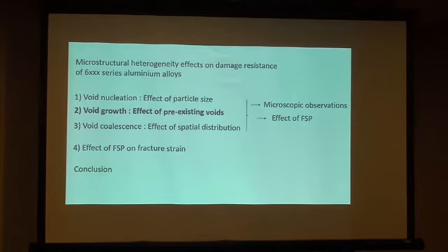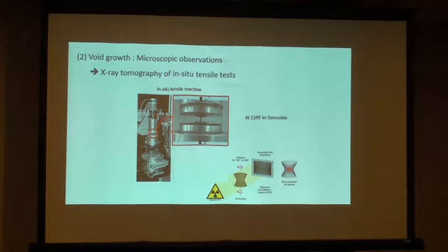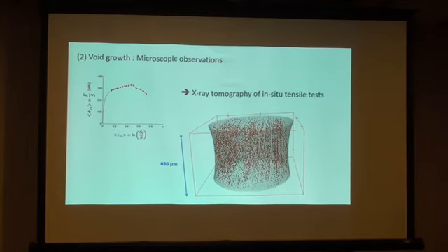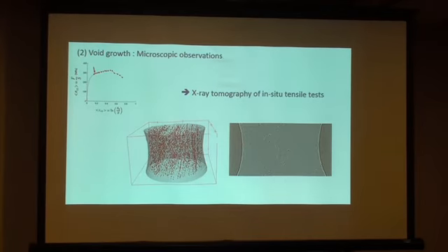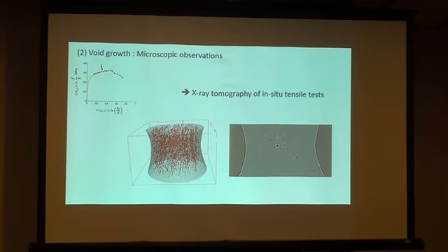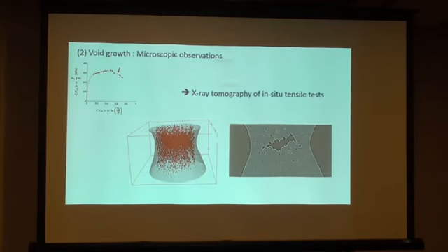So now let's have a look at the effect of initial porosity on the damage evolution. To study this, we performed some in situ tensile tests at Grenoble, and this is a typical result. This is the studied part of the specimen. Here you can see the measured tensile curve on the small tensile machine within the tomography. On the left is a 3D view, and on the right is a central section of the specimen. What you can see, of course, is that as you increase the strain, the voids grow. At some point, some of them coalesce, and then at the end of the process, you have a lot of coalescence. You get a micro crack, and then you finish with a classical shear lip, and the specimen is broken.